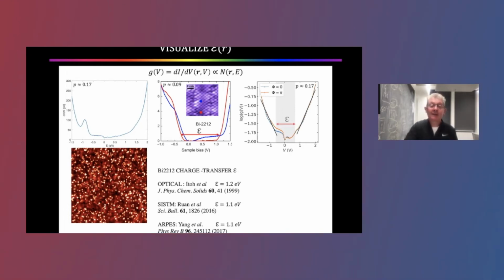It's not that complicated. At the top of the P band, the tunneling density of states zooms up extremely quickly. And at the bottom of the empty D band, the tunneling density of states zooms up very quickly. And you can measure the energy difference between those two bands. We did it long ago when looking for the dopant atoms. And Yayu Wang has done a beautiful study of very lightly doped cuprates where he measures the same thing, the charge transfer energy. And in our study today, we're using the same technique. We just measure the energy difference between the top of the P band and the bottom of the D band. And the vertical scale in the top right-hand panel here is logarithmic. So the density of states is screaming up exponentially. Your ability to measure this epsilon is very, very good.